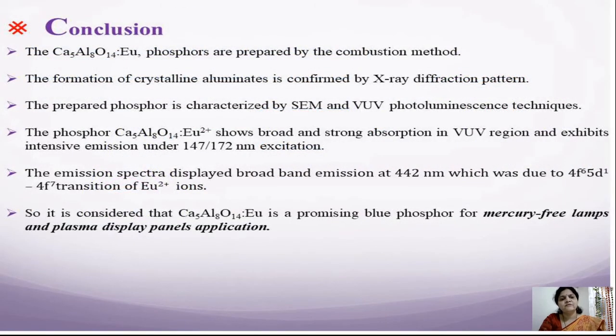Conclusion: the Ca5Al8O14:Eu2+ phosphor was prepared by the combustion method. The formation of crystalline aluminate is confirmed by X-ray diffraction pattern. The prepared phosphor is characterized by SEM and VUV photoluminescence techniques.